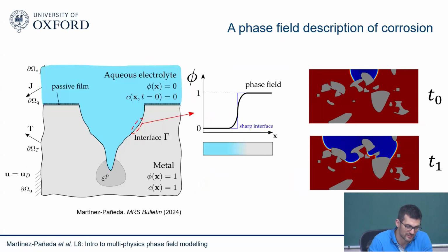And then the idea is as you see here, so you have basically now the two variables that I mentioned before. So you have the concentration of metal ions, which is 1 in the metal, and then it starts going towards 0. And then you have the corrosion front, which is described by the phase field, which takes a value of 0, in this case in the aqueous electrolyte, so in the seawater, and 1 in the metal.